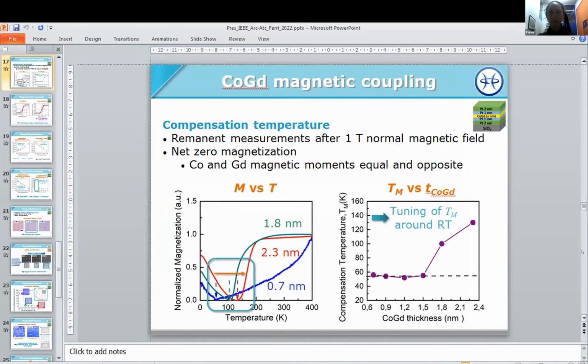And so we measured what is called the compensation temperature, which is the temperature for a ferrimagnet at which you still have an antiferromagnetic coupling between the two sublattices, but the magnetic moment of each element is equal. And so actually you don't have any net magnetic moment. So we did some measurements at remanence after applying 1 Tesla normal to the plane. And you can see as a function of temperature that even for 0.7 to 2.3 nanometer, we have each time a minimum of the magnetic moment.